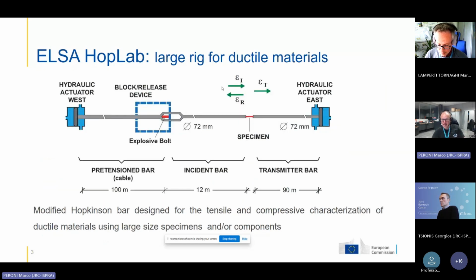This is the diagram of the large facility that we have, the one that is 200 meters long. It's not so simple to understand for people who are not involved in high strain rate testing, but substantially the operating principle is quite simple. There is a sort of elastic cable that is pre-stressed and fixed at one extremity with an explosive bolt. When you quickly release it, these ends move very fast in one direction, and to these ends a bar is connected. In this way, you can produce a tensile pulse or a compression pulse that goes to the specimen and applies a very rapid load to the specimen.